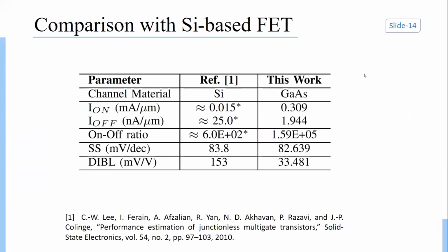Here we can clearly see that the results of gallium arsenide dominate over silicon. We used a reference of recent works, and from the left side we can clearly see that the silicon results I on is less than gallium arsenide results, and I off is also tremendous in this work. On-off ratio is tremendously good, and SS is slightly low, whereas DIBL is almost 1/4.